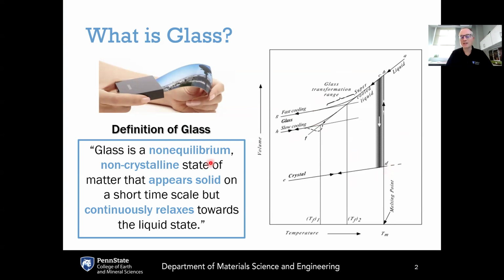The fact that glass is non-equilibrium means that it is a thermodynamically unstable state. That means that it is continuously relaxing towards its metastable supercooled liquid state. And it also means that we need this additional order parameter to describe the thermal history of the glass, which is this fictive temperature here, TF1 and TF2.